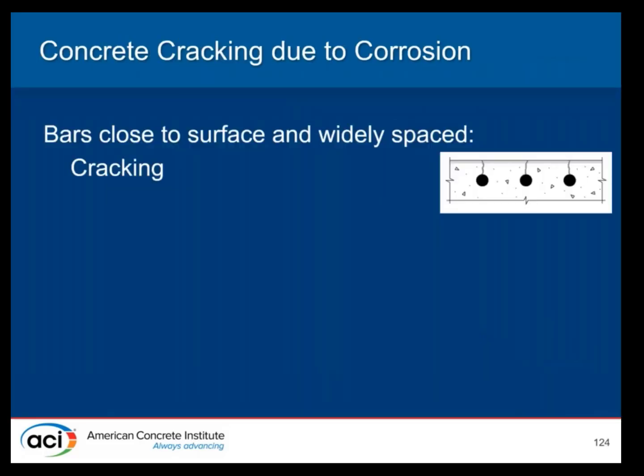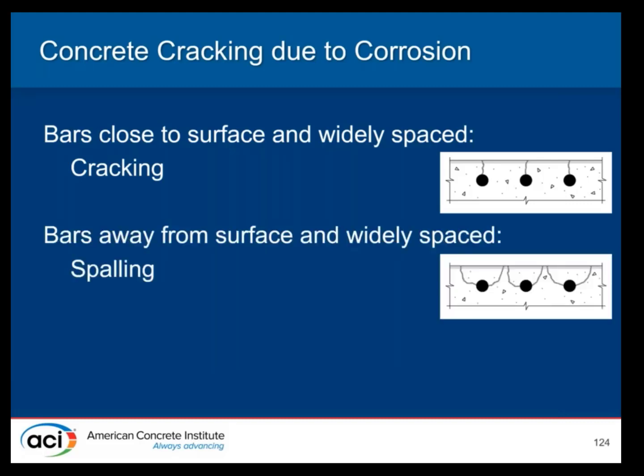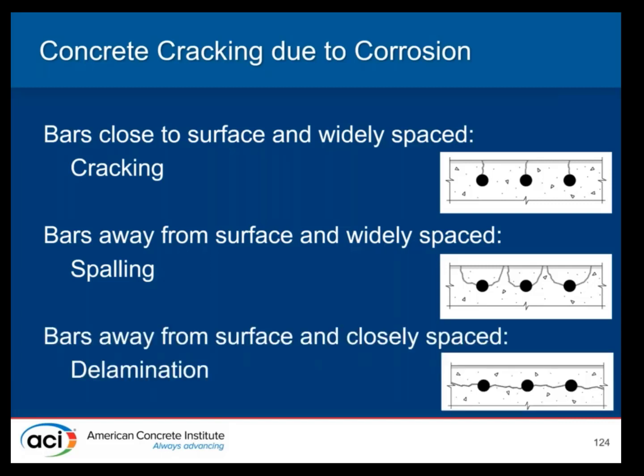So concrete cracking due to corrosion: if we have bars close to the surface, widely spaced, the bars will tend to have vertical cracking. If the bars are away from the surface, then wide spacing will tend to get localized spalling. And the bars away from the surface and more closely spaced will get a delamination. So when we're thinking about our assessment, those are different types of cracking patterns that we have to be aware of and understand the implications of what they mean.